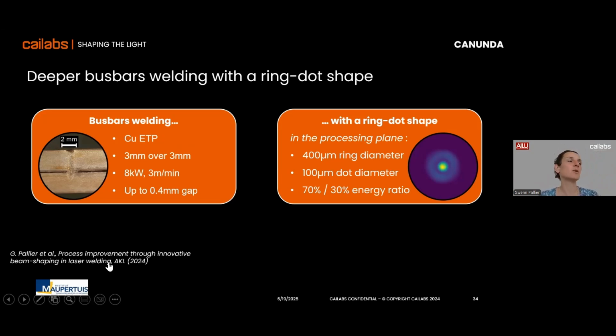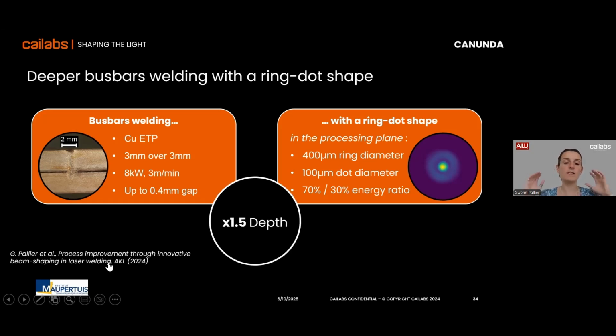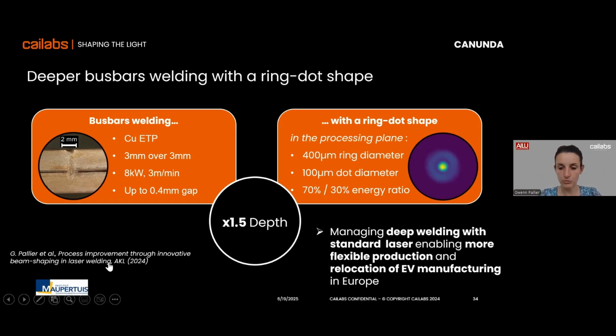And not only is it not possible to do that without beam shaping, but even the other state-of-the-art technologies to do this kind of welding were also not stable at that low speed. And somehow we managed to do it. So at similar power, 8 kilowatt, we managed to weld 1.5 times deeper compared to no beam shaping, which was a good improvement.